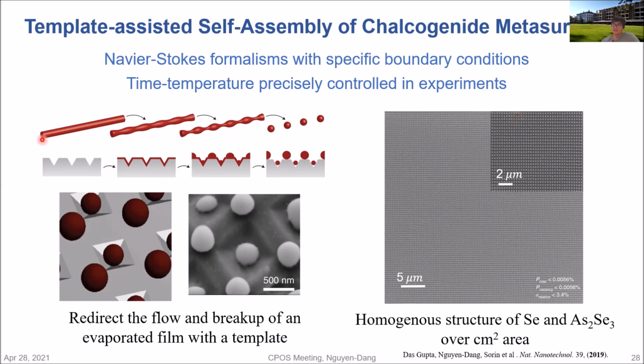For example, in this schematic, I show you how a rod of water, or a rod of the material, can break up when you decrease the viscosity, and it starts to break up into droplets. The same thing happens if you evaporate a thin film of material on top of a patterned substrate, and then you anneal it to reduce the viscosity. So basically, it starts to break, and because you have certain patterns, it breaks in the places where you want it to happen. If we control the processing techniques very well, we can have very homogeneous structures. For example, I show here the work done by a grad student. He really created a centimeter square of chalcogenide metasurface glasses.